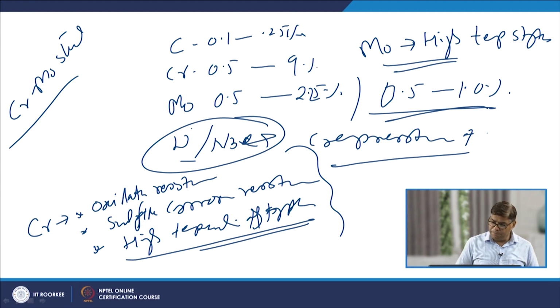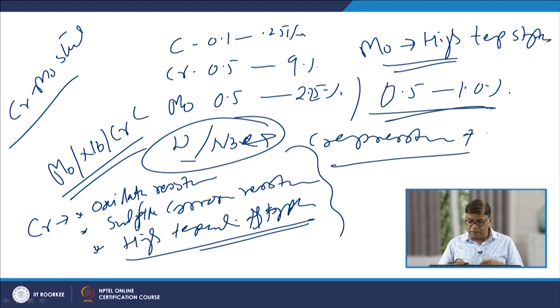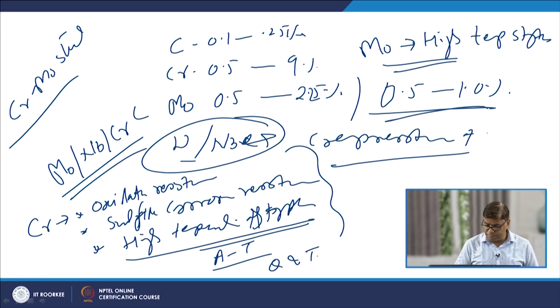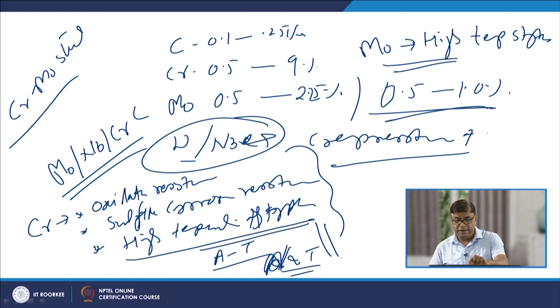When these elements are present, because of their good affinity with carbon, they tend to form their carbides, like molybdenum, niobium, chromium carbides, etc. Some of these carbides are good because they are stable and they do not decompose even at elevated temperature, and that is why they help in imparting good resistance to creep as well as high temperature strength. These steels are used in different conditions, like annealed and tempered, or quenched and tempered condition, or the normalized and tempered conditions, and these offer quite good strength and ductility.